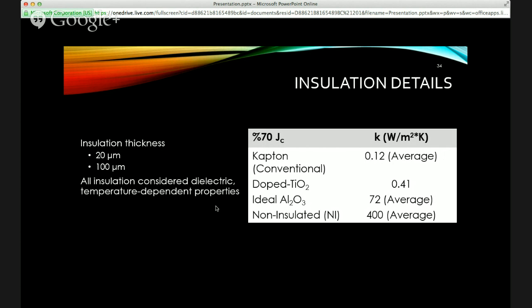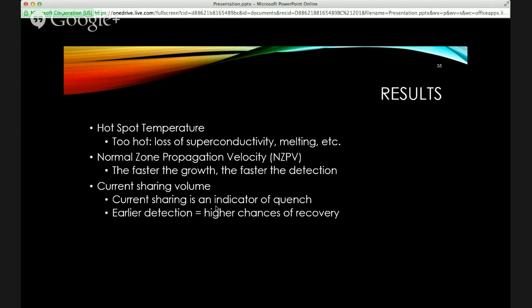But I also looked at ideal alumina because of its high thermal conductivity, and a non-insulated case, meaning there's no insulation, so it's essentially copper on copper. So this thermal conductivity is what you would see for copper. And these are average values. The different results here are just a smaller set, these aren't all the results. This is the more important stuff.